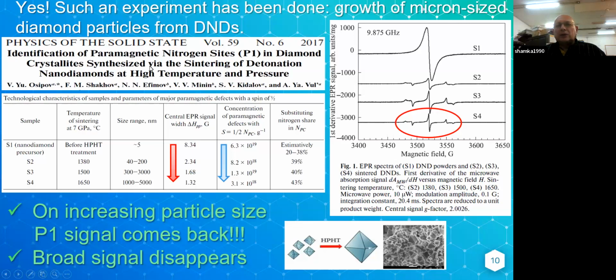They use detonation nanodiamonds of 5 nanometer size in specific conditions. It means the sintering at high temperature and pressure of detonation nanodiamond to get larger crystallites. And they succeeded, and look what happened there. They start from detonation nanodiamonds. This is the signal. Then, changing time and temperature conditions, they get larger crystallites from 5 nanometers to about 5 microns, from 1 to 5 microns in this case.